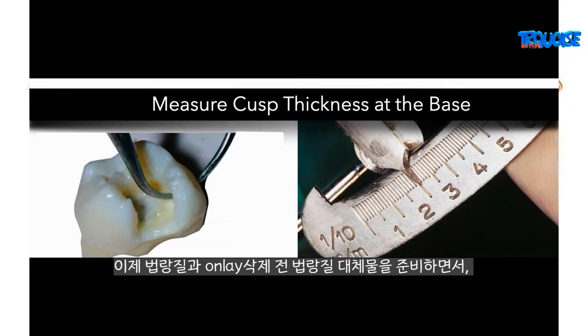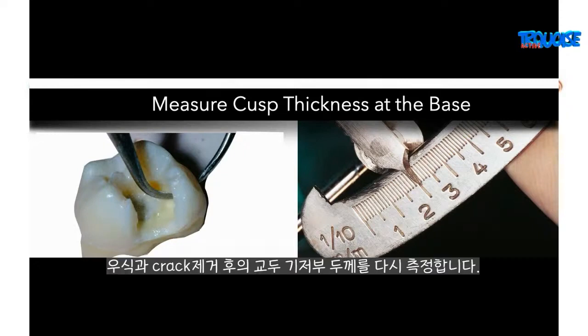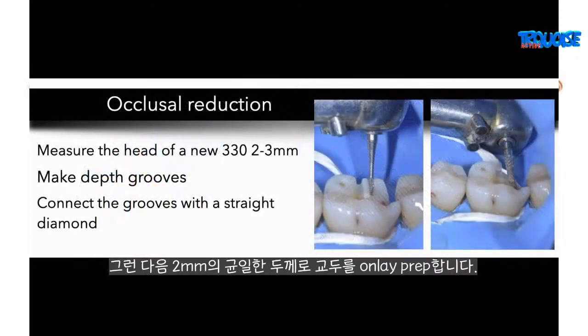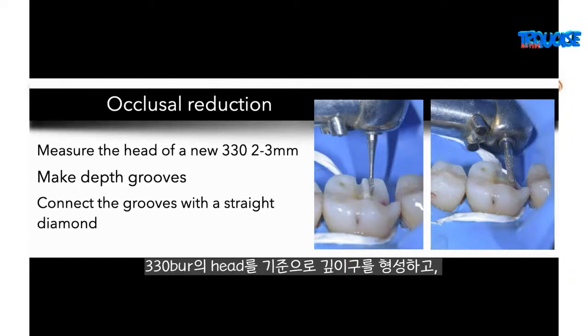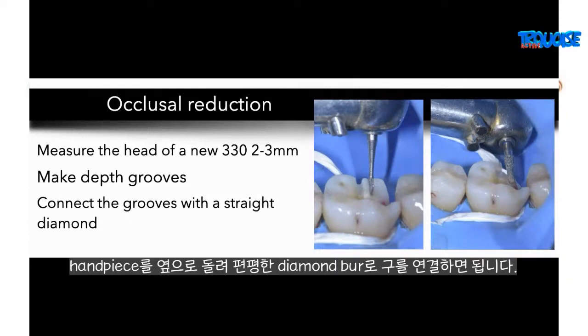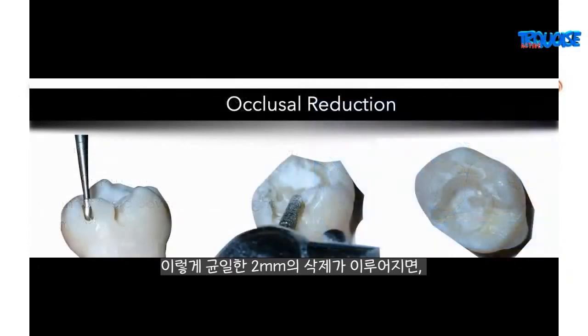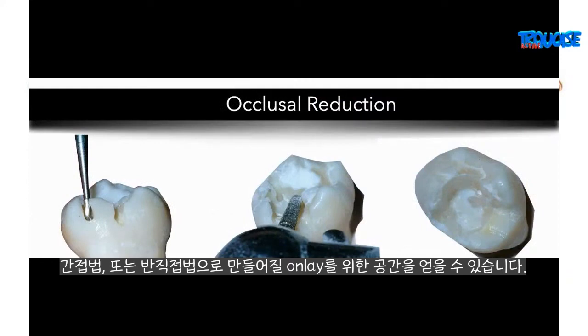And now as we prepare the enamel, or the enamel replacement, our onlay preparation, we would again measure the thickness at the base of the cusp after caries removal and crack removal. And then we onlay the cusp at a uniform thickness of 2 millimeters by measuring the head of a 330 burr and making depth grooves with that. And then we would turn our handpiece sideways with a flat diamond, and we connect the grooves with a straight diamond. This gives us a uniform 2 millimeter reduction and gives us room for our onlay that's made semi-directly or indirectly.